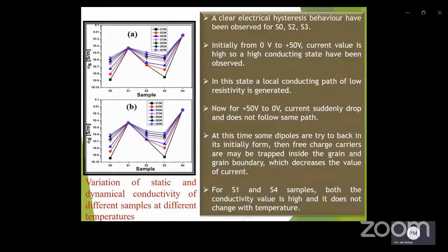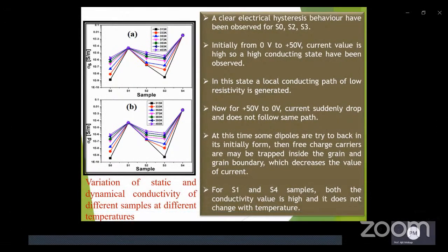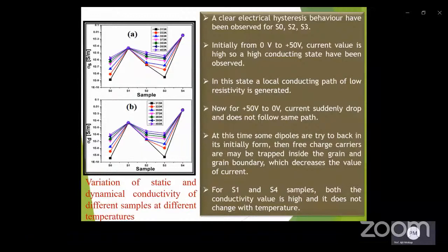Static and dynamic conductivity of the different samples are plotted here. It is observed that for S1 and S4 sample, the conductivity value is high and it does not change with temperature, whereas other samples show the temperature variation. So by changing the functionalized group of MWCNT, we find different conducting behavior of the functionalized MWCNT PVDF film.